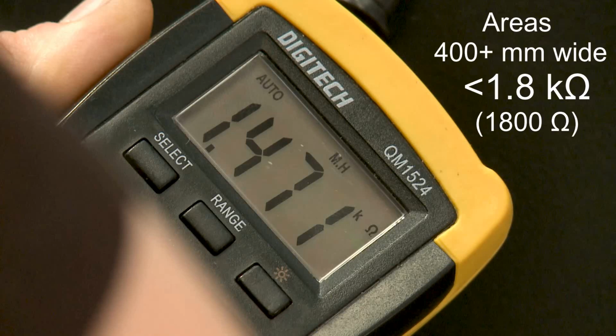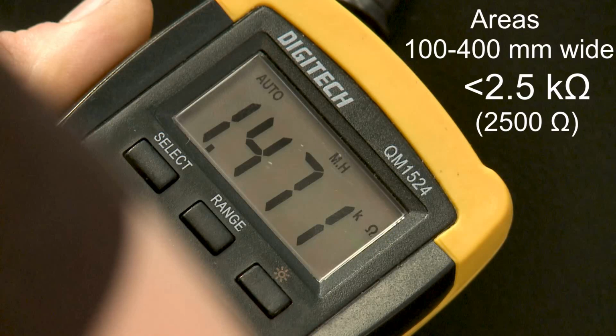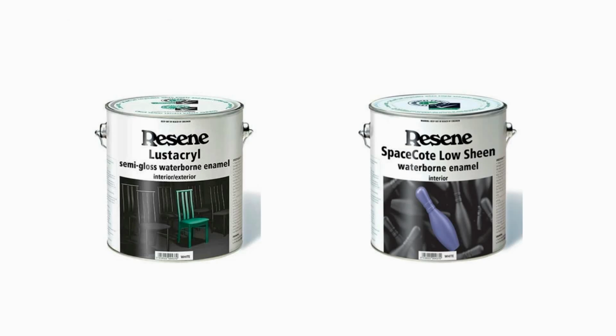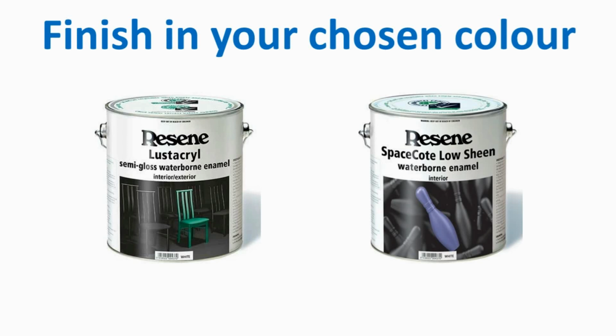All measurements should be less than 1800 ohms, 1.8 kilo-ohms, for areas wider than 400 mm, and less than 2,500 ohms, 2.5 kilo-ohms, for areas between 100 and 400 mm wide. Finally, finish the job with Resene SpaceCote or Lustacryl.